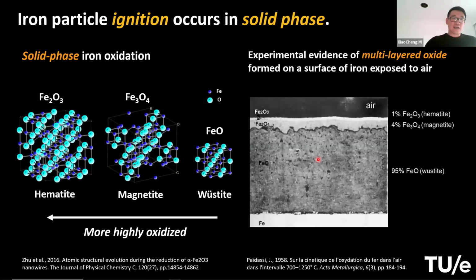And this is a picture taken from a metallurgy study back in the 1950s. It shows the oxide layer that grows on top of an iron surface exposed to air, which is an oxidizing gas. You see that nearly 95% of this oxide layer is wüstite, FeO. And then there is a thinner layer of magnetite, and a very, very thin layer on top, which is Fe2O3, hematite.